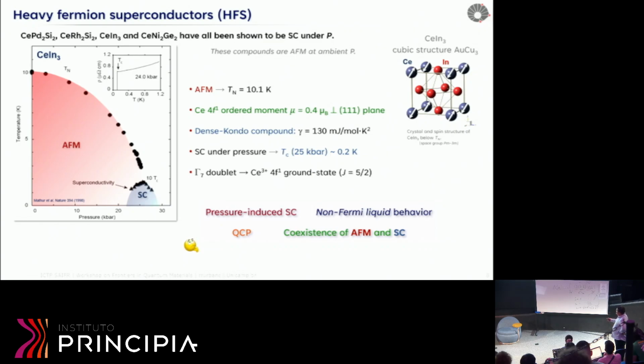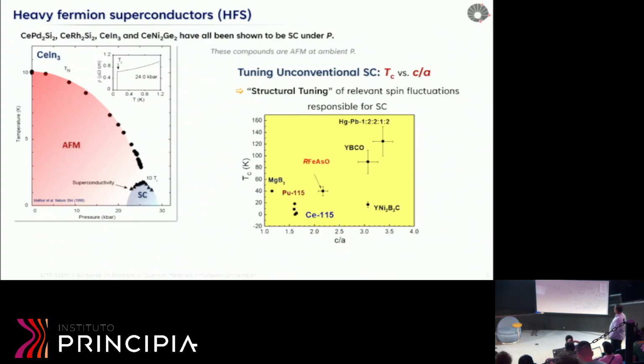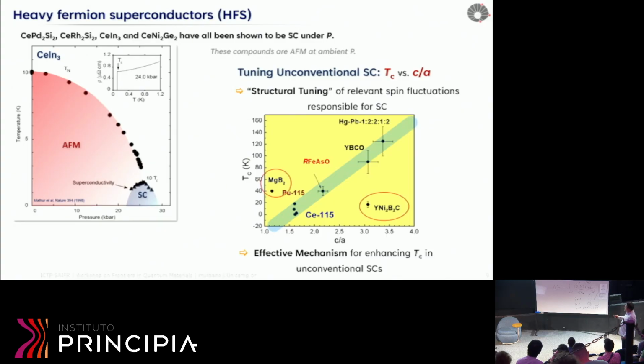So there are all these behaviors, these underlying physics going on with these materials, which makes it very interesting. So here I show you some plot that is a bit of an idea, but for many a bit controversial. But we can think of Tc with a linear relation with the ratio between the lattice parameters, c over a. And we understand for the unconventional superconductors that the higher this ratio is, the larger the Tc we can reach, which is not true for BCS superconductors or conventional superconductors.